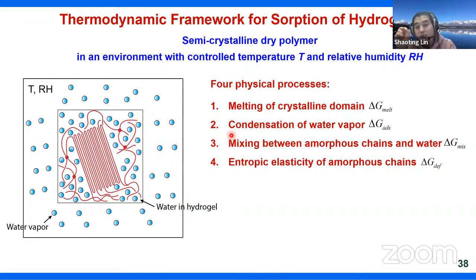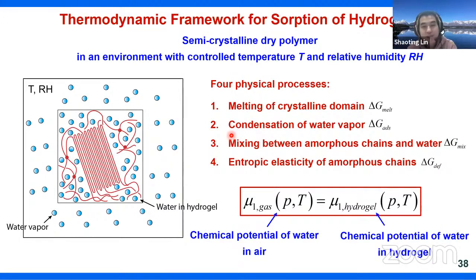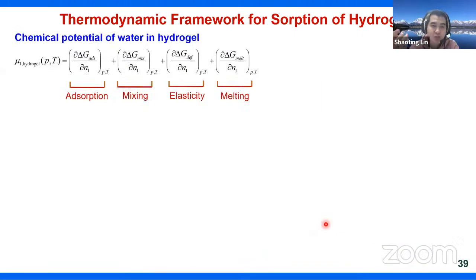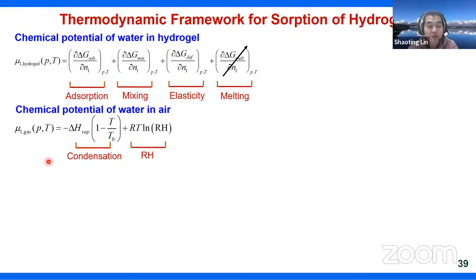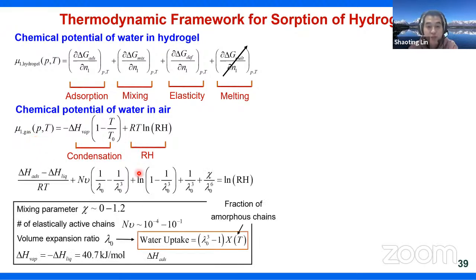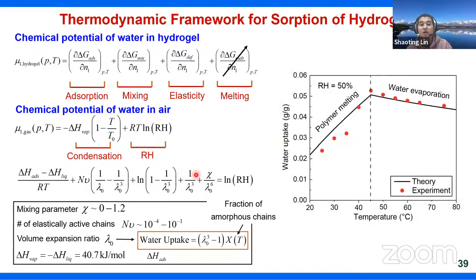And to solve this problem, we impose that the chemical potential of the water in the gas state is equal to the chemical potential of the water in the hydrogel state. By solving for the chemical potential in the hydrogel and the chemical potential of the water in the gas state, we get the governing equations. By putting in the real numbers for the PG network, we can solve these equations at different temperatures, right? So we can calculate the water uptake as a function of temperature.